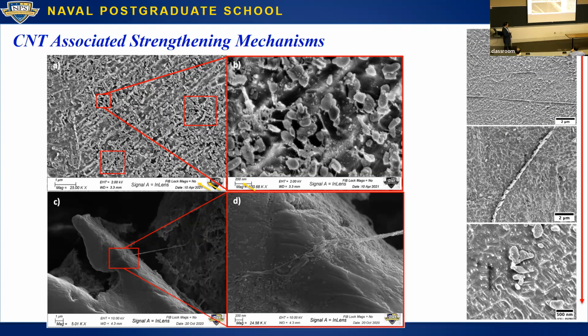We also saw intact CNTs. So these are essentially CNTs bridging a very small pore in the sample. And as far as we know, we're the only study so far. There's one published this year on stainless steel that got it done. But in terms of titanium, the only studies that have tried this have essentially lost all of their carbon nanotubes, and they're left with nothing but carbides. We actually have some nanotubes remaining, which is what we wanted in the first place. We wanted more of a fiber type reinforcement.